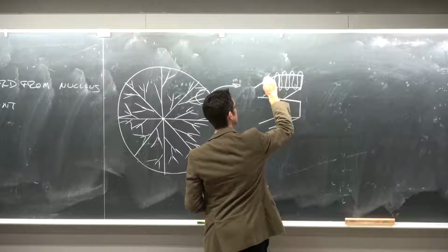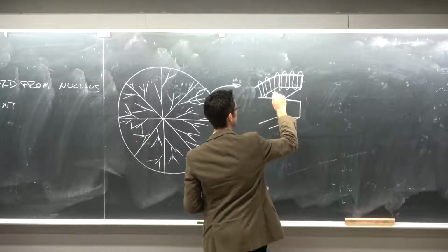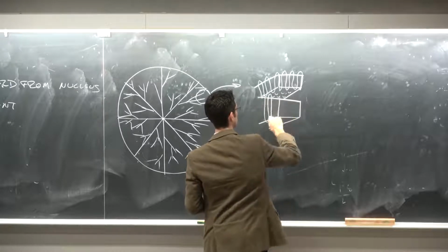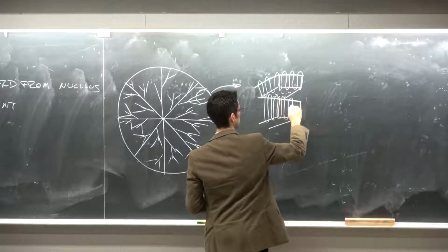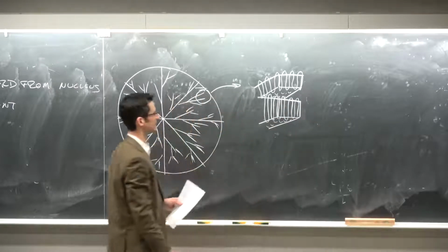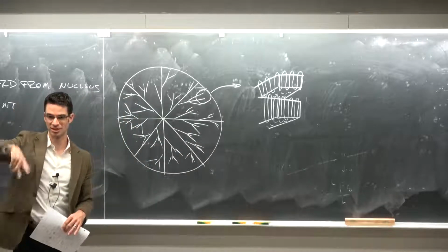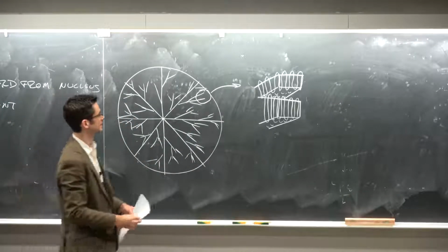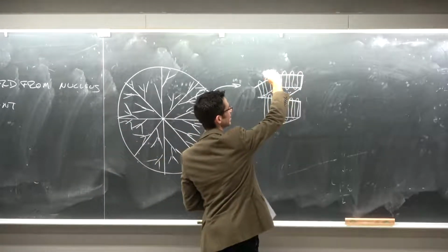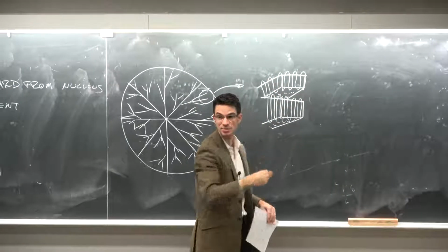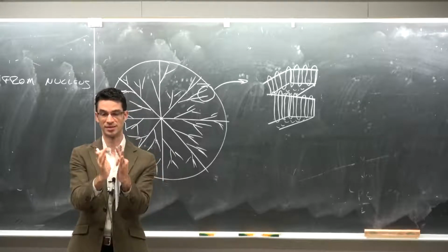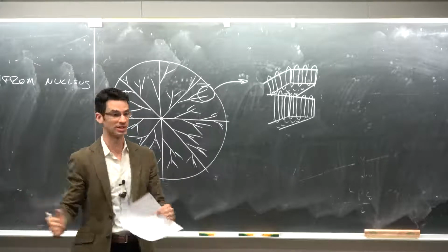The polymer chains form these hairpin turn structures that fall back on themselves, they form these 180-degree turns. In some cases, this is a particularly well-ordered structure. Sometimes you'll have loose ends that exit the switchboard and come in somewhere else, but they're still within the crystallite. The axis of the polymer chains are side by side.